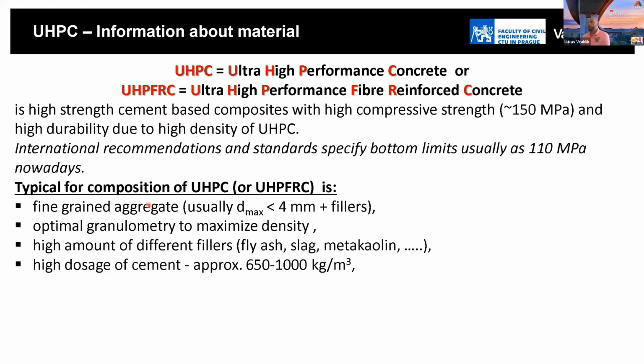Also, we use a high dosage of cement. Approximately, it is 650, maybe more than 650, up to 1,000 kilograms per cubic meter. Comparing to normal concrete, for normal concrete we use, for example, 400 kilograms per cubic meter. That means that the dosage of the cement is approximately 2 times higher compared to normal concrete.